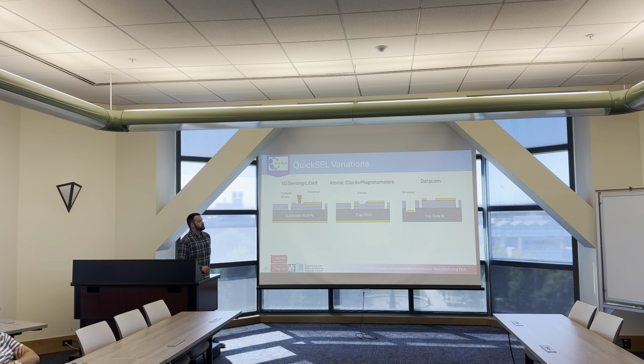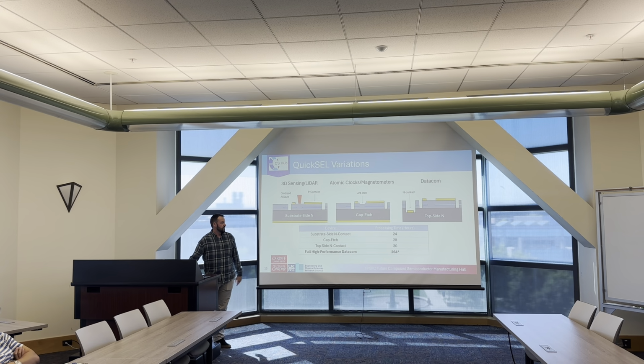And then some epi structures designed for datacom applications, so they can be grown on a semi-insulating substrate. So both the contacts need to be on the top side then. So that requires another etch, another deposition on top, which obviously affects the processing time, but still 30 hours for the most complicated QuickSEL. And then in comparison to a full high performance datacom VCSEL, it's a huge reduction.